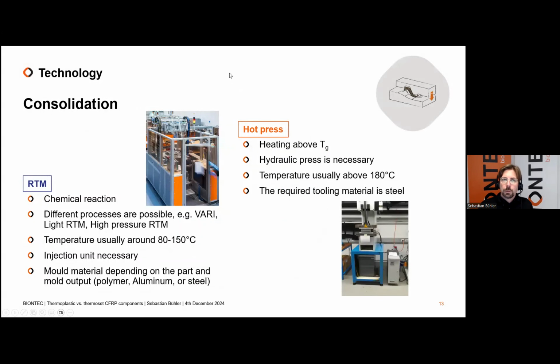Coming to our very important point, the consolidation. You see, blue is always the thermoset route, and orange is the hot press or the thermoplastic route. As you can see, for the RTM, we use our own machines. Of course, we have a chemical reaction. We mainly use light RTM or high pressure RTM. That depends a little bit on the thickness of the part. And for prototypes, of course, we can use a Vari system. Temperature is usually around 80 to 150 degrees for our main parts. Some parts are a little bit higher, but mainly we are around this temperature area.